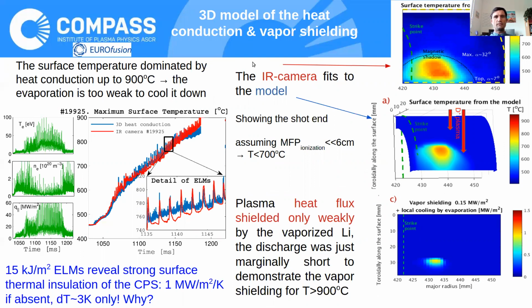So the 3D model of the heat conduction and vapor shielding shows here the main results. This is the infrared camera image. This is magnetic shadow, so the plasma was exposed only to this top of the target. The plasma was going like this. So it's a shallow angle and a pretty high angle up to 40 degrees, here in this case 30 degrees. And the maximum values across these two images are shown here in time. You can see that they correspond very well, the heat conduction model and the infrared camera. Even the details of the ELMs you can see here.